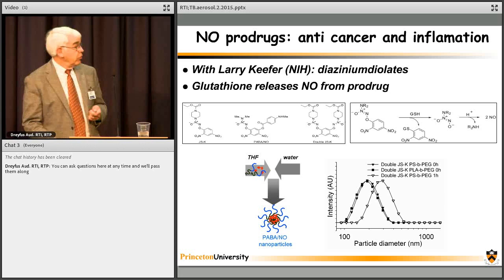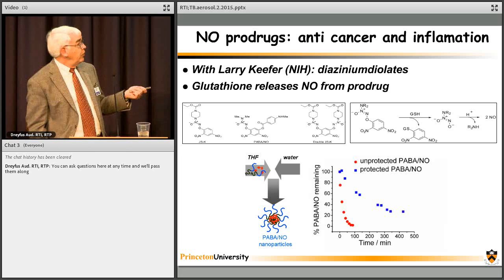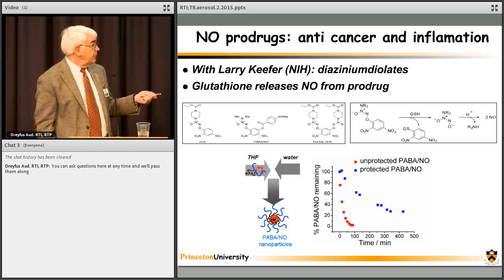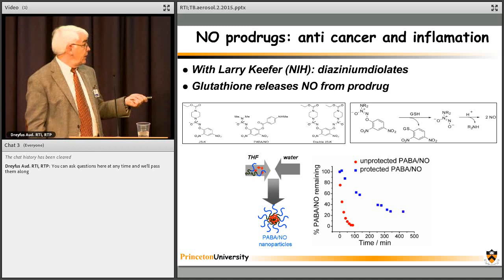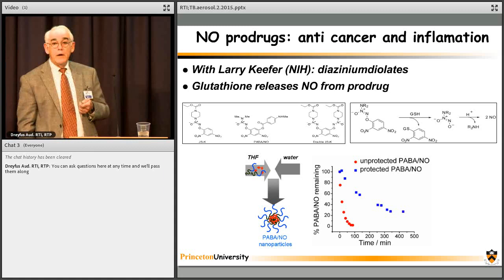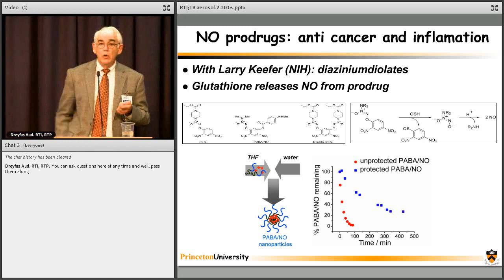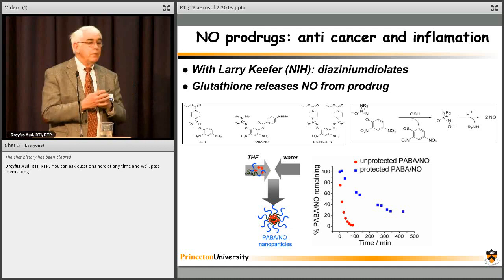And then in the animal studies, this shows the NO release rates. If you take his NO prodrug initially, just the prodrug itself in DMSO, inject it, and look at the NO release rates, within 25 minutes you've lost all the NO. The release is way too fast. In our protected nanoparticle, you can see the half times here are about 120 minutes. And so that gives you enough time to, in fact, administer these things. And then the cancer tumor study showed that these were effective. Okay, so what we've done is by putting things in the core, we control their bioavailability, allow them to circulate, and keep them from being cleared.